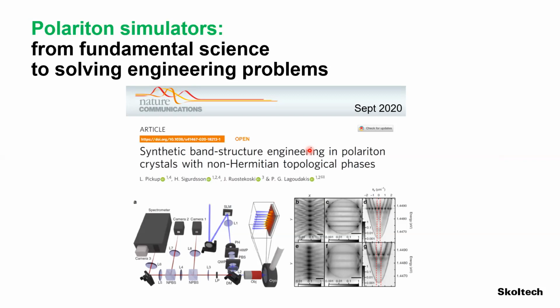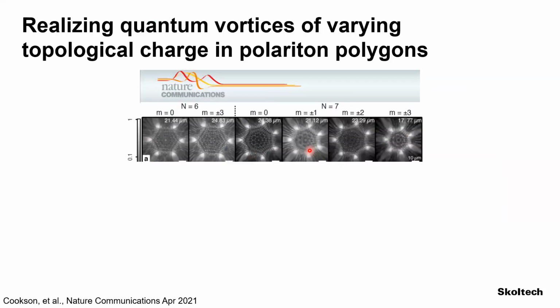We can create topological charges by creating polygons where the phase, as it goes around and you close the loop, goes from 0 to 2 pi, so you can have a quantum vortex as you go around the polygon of condensates. But as we showed here, we can create giant vortices. We can create vortices of multiplicity 3, higher order topological states. In this system, we can measure the reciprocal space, extract the phases, etc.